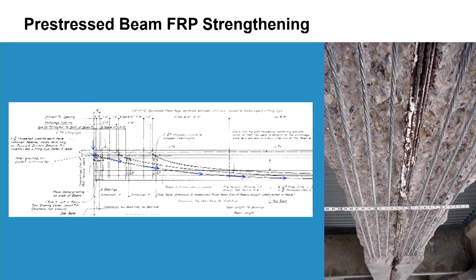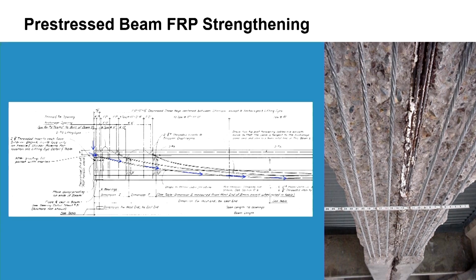From what we've discovered in the as-built, the two top post-tensioning ducts daylight at the top of the beam and then are encased in the deck, so they're not exposed to any water intrusion. But for the plug at the end of the bottommost post-tensioning duct, if there are any cracks or failure of that in the open joints, then water can start to slowly intrude through the grout. They did discover that the grout had cracks and gaps in it. So over the 60 years since this has been constructed, that post-tensioning duct has corroded.